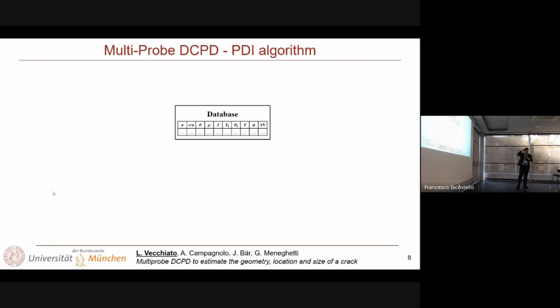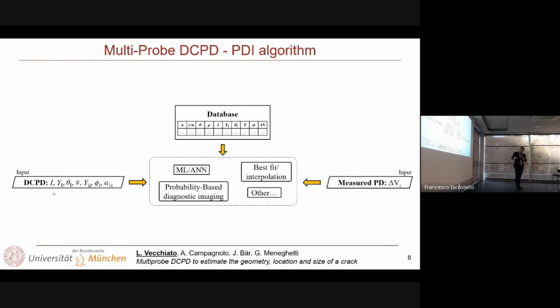So how to do? The idea came not a long time ago, and it all started by assuming that for a moment we have a certain database for different crack configurations. So let's assume we have, for a certain crack depth, length, position, and shape, and for a certain position of the probes and the wires of the probes, the corresponding potential drop. So we have a certain database that sweeps along many different configurations, all possible configurations in a certain way. And then add some more information, which is how we have filtered, configured and set up the potential drop measurements, and what are the measured potential drops in the experiment. Put the database information along with the measured potential drop in a certain algorithm, about which I will speak in a minute, and then perform some calculations to have an estimate of the crack depth, crack shape, and crack angular position in this case.